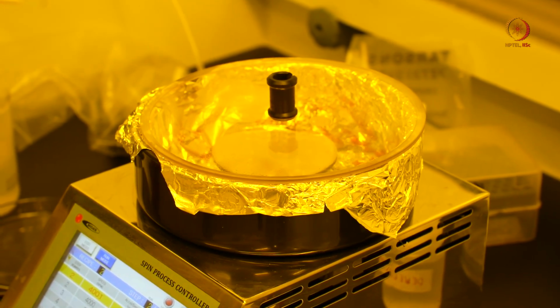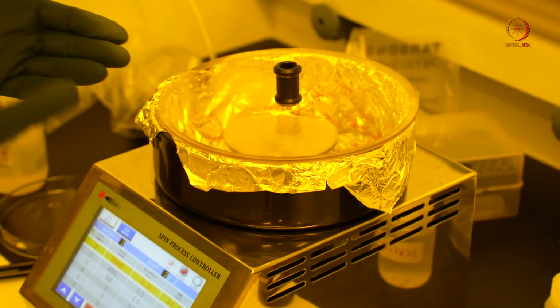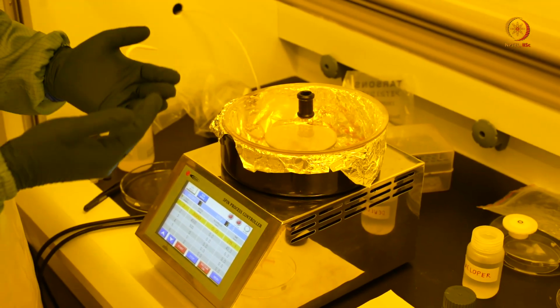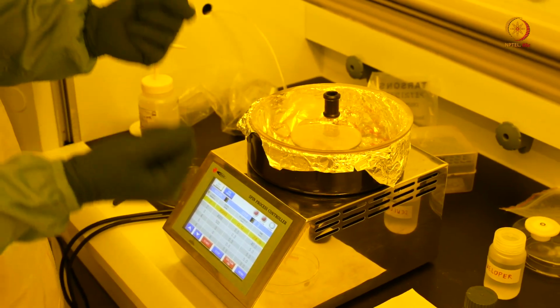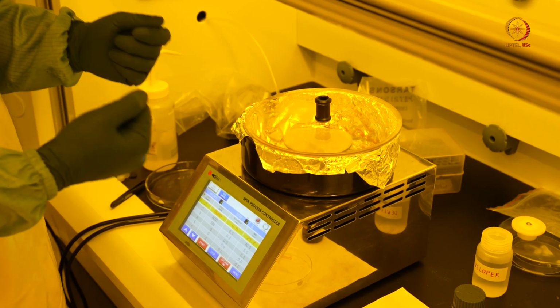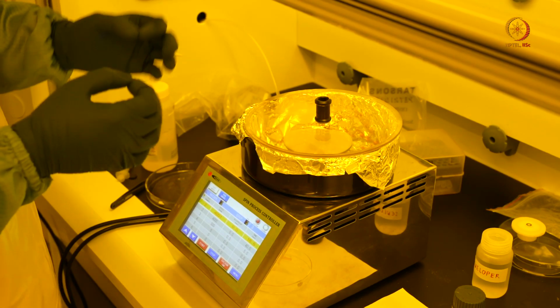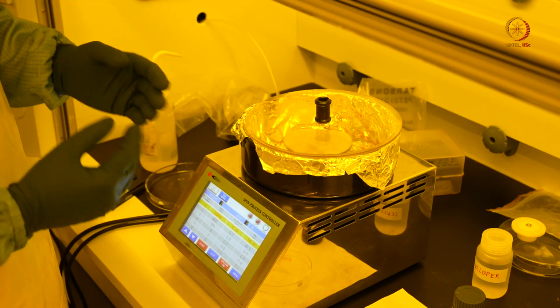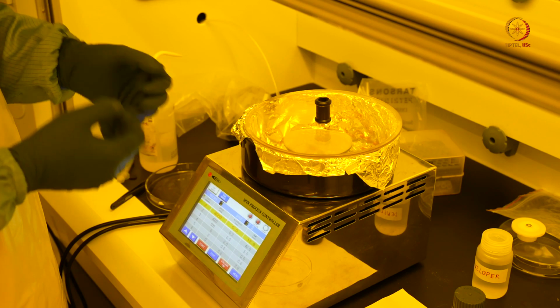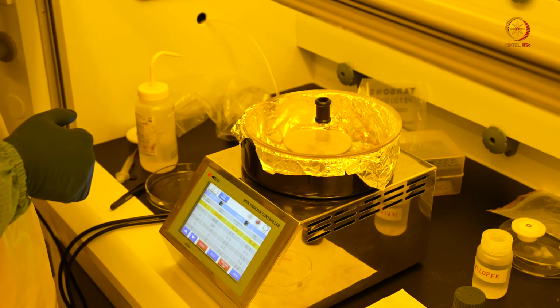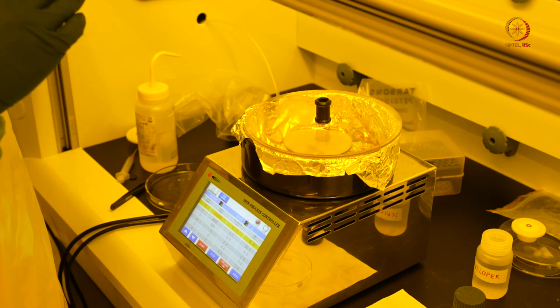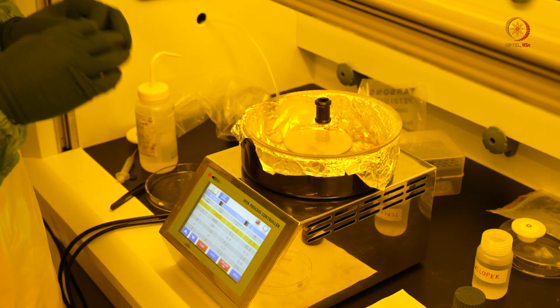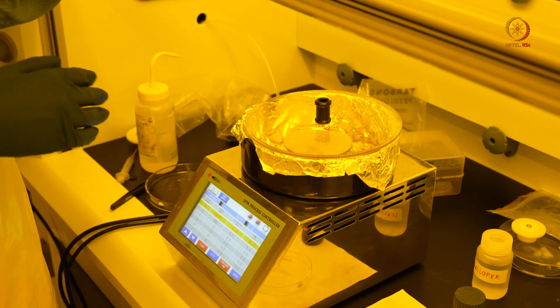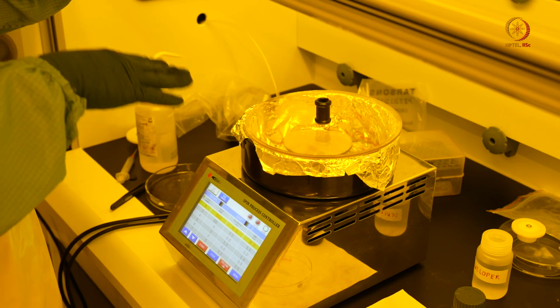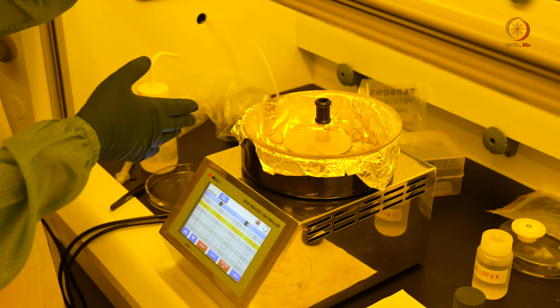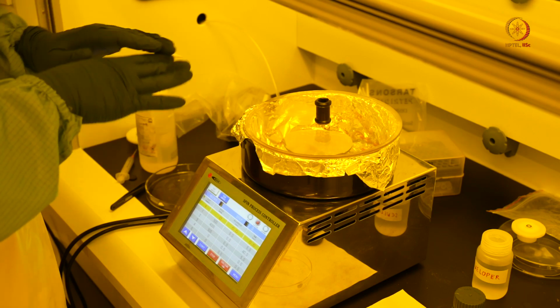The physics behind spin coating is very interesting. You can always go and read some extra materials on it. It will be really fun to see how viscosity, temperature, humidity, so many different factors affect how we can get very uniform thickness across the wafer. And the thickness of photoresist is a very critical parameter in the photolithography process, which we will see in the next step. So getting very uniform photoresist from the center of the wafer to the edge is very critical. And as per the data sheet, when we spin coat this specific photoresist at the suggested RPM, we get around 95% uniformity across the wafer.